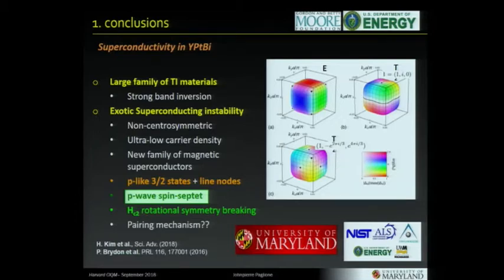Other than what's typically done now, which is to think about a proximity effect induced state from a regular superconductor into some topological material, and that's not even known for sure. Like in bismuth selenide, if proximity-induced bismuth selenide is a strong topological superconductor or not, or like what I showed, the strontium or copper doped bismuth selenide. So this is a good question. How do you do that?